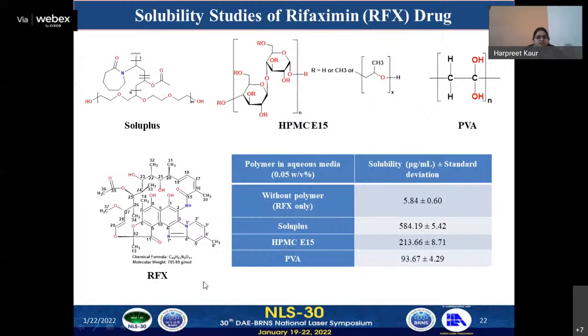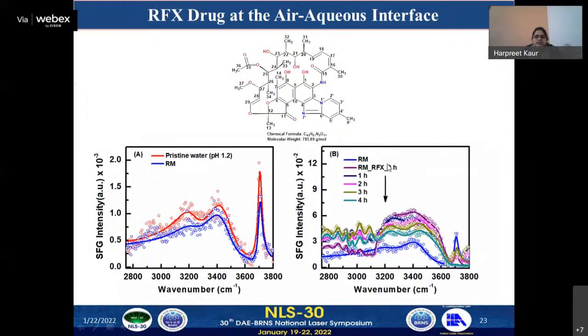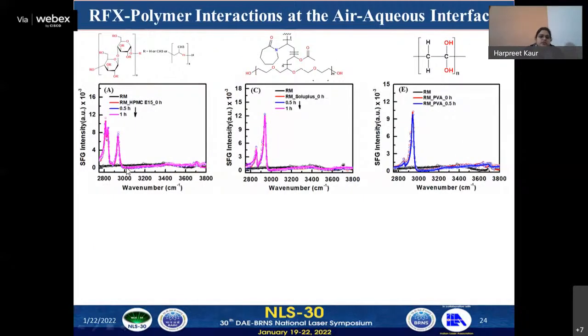This is the molecular structure of rifaximin. The solubility is enhanced in the presence of these polymers. And further, the SFG studies have shown that on addition of this rifaximin drug to the aqueous system, there is an overall enhancement in the SFG intensity in the OH stretching region, which confirms that there is ordering of the interfacial water molecules of the relevant media in the presence of the drug. Further, we have probed the effect of polymers on the interfacial structure, from which we have found a sharp, dominant signature in the CH stretching region, which confirms the surface coverage by these polymers at the air aqueous interface of the relevant media.